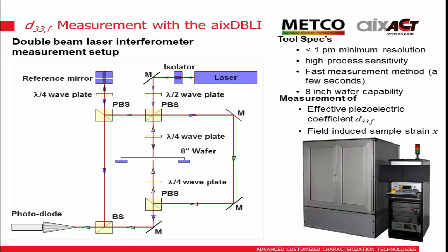So the principle here - we've already seen two types of interferometers. This is a double-beam laser interferometer: we have a measurement beam that comes from a stabilized laser source, goes to the top of the sample, then is directed to the bottom of the sample and interferes with the reference beam, and we get the difference between the top and bottom motion - the elongation of the sample between the two beams. So basically we have a point measurement, but it measures the point on top and bottom, so we exclude the sample bending.